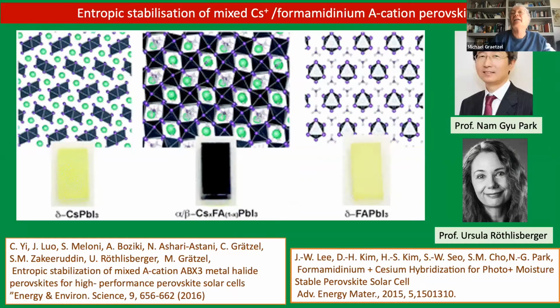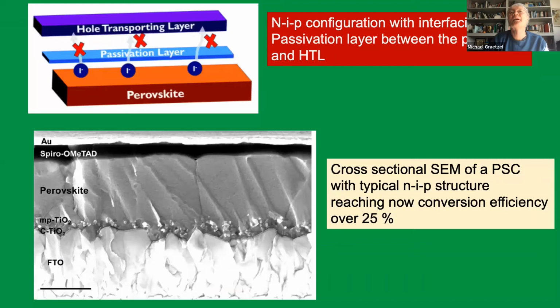And then also the cesium, it's an amazing observation. You take cesium lead iodide. It's a yellow substance at room temperature. The formamidinium lead iodide also, its stable form is yellow, but then you mix them, you grind them in a mortar, and you find that a black powder is formed by mechanochemical synthesis. That's amazing, such a clean reaction, and we were also involved in this research.